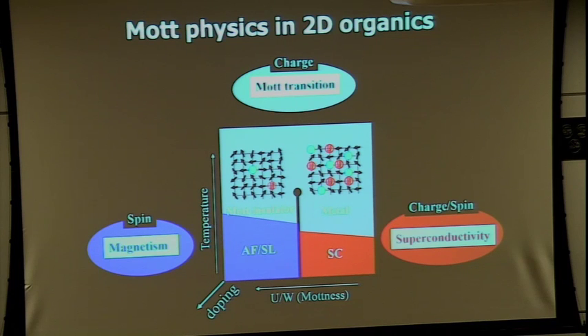So these materials span the phase diagram of the Mott transition as a function of temperature and correlation strength. This is the first order Mott transition boundary. You can explore the spin physics in these regions and the charge physics, namely the Mott transition. Then at high pressures, the metallic phase stabilizes and superconductivity appears at low temperature.